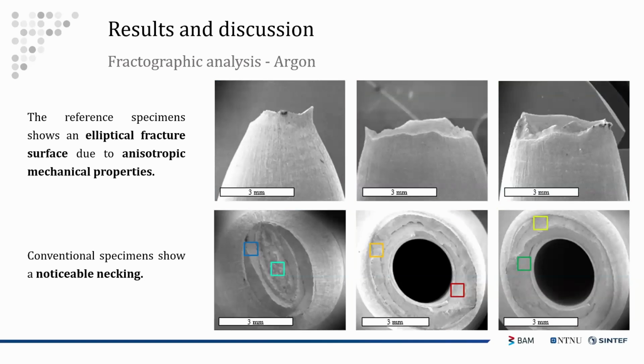Considering the test in a reference environment, moving from the left-hand side to the right-hand side, we can see that the solid specimen shows a noticeable necking and an elliptical fracture surface that results from the anisotropic mechanical behavior due to the microstructure of the steel. But we can see the same elliptical fracture surface, even if with lower necking, also for the hollow specimen in drilled and reamed configuration.